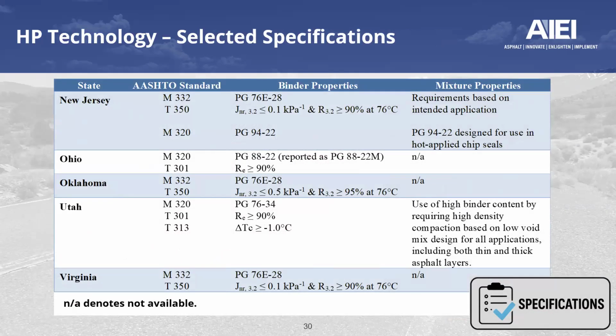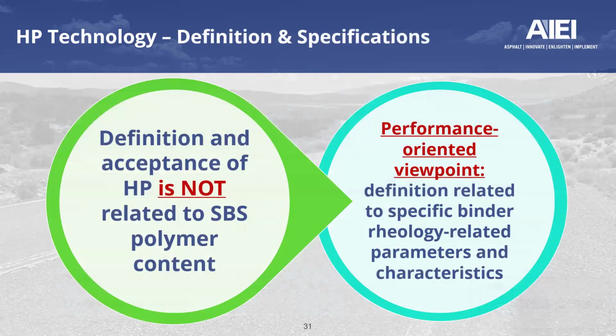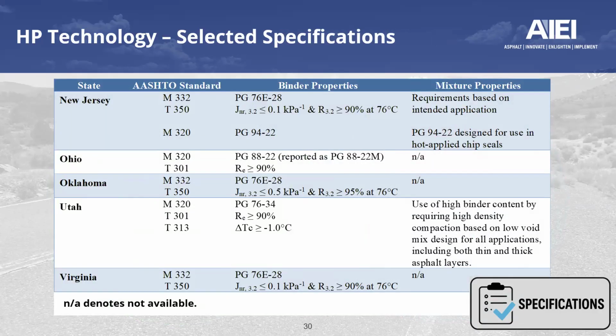Taking a brief look at the type of specification, these are the specifications from the 5 states that we visited. I want to talk first about the last one, Virginia. Virginia follows M332, and that's a PG76E-28. They do have a requirement in testing for the MSCR. The non-recoverable compliance at 3.2 kPa is a maximum of 0.1 kPa^-1, and they have a requirement on percent recovery of a minimum 90% at 76 degrees C.